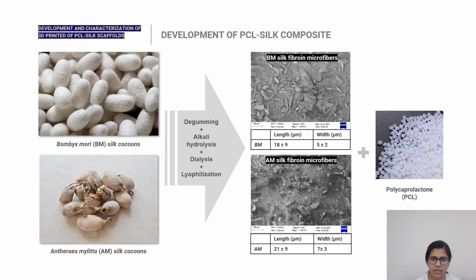So in our study, we have developed a single protocol to form silk fibroin microfibers from both the cocoons. Initially a process of degumming, then alkali hydrolysis was done, then dialysis, and then lyophilization to form the silk fibroin microfibers. As you can see, these are the images of the silk fibroin microfibers, Bombyx mori and Antheraea mylitta. The length and width for Bombyx mori was around 18 microns and 5 microns respectively. For Antheraea mylitta, 21 microns and 7 microns respectively.